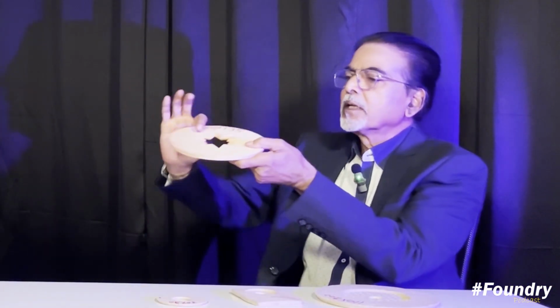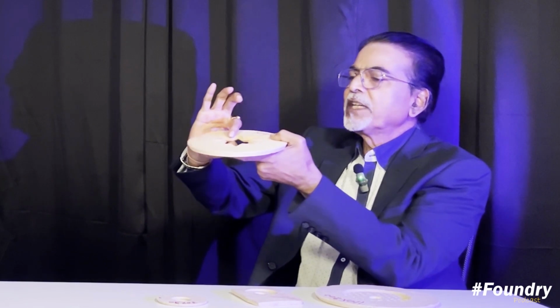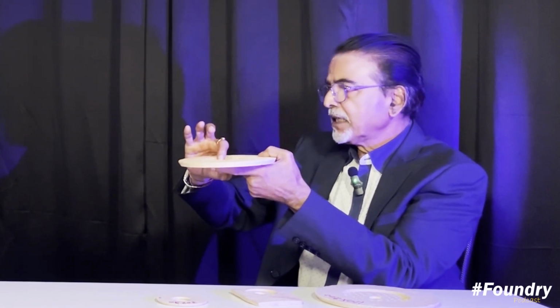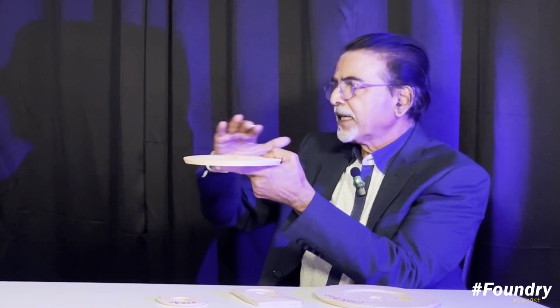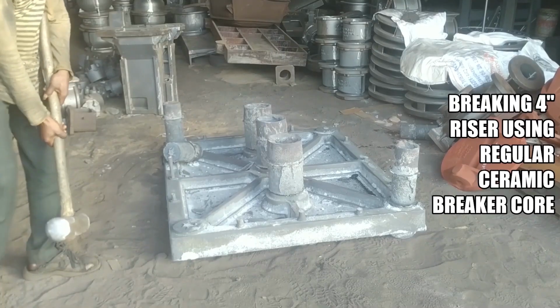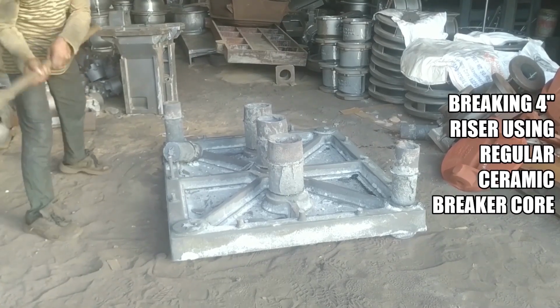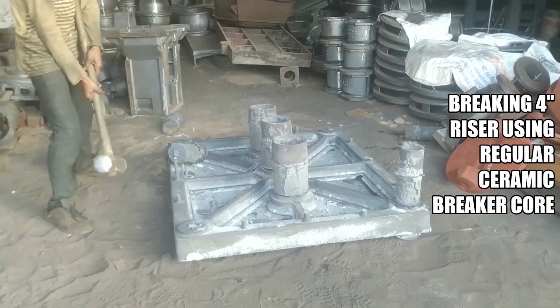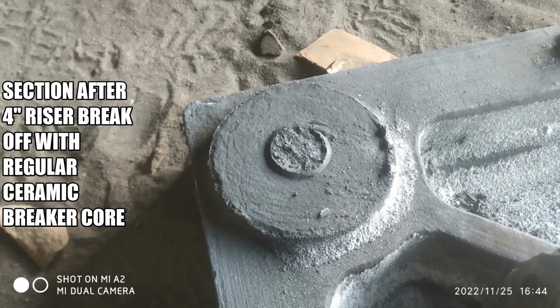You can see from here, it is pretty sharp. This portion is very sharp. So this makes sure that the riser breaks only at that point, and not below it, not into the casting. So your casting is never rejected because of wrong breakage.